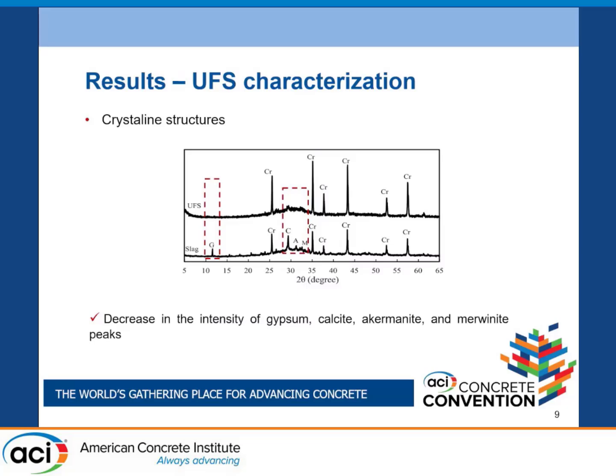The second one is the crystalline structures of the slag before grinding and the UFS after grinding. Here we saw a decrease in the intensity of some peaks, such as gypsum, calcite, akermanite, and merwinite. They were in the slag, but after ultrafine grinding they were amorphized. And the amorphous content of the UFS increased a little compared to the slag.